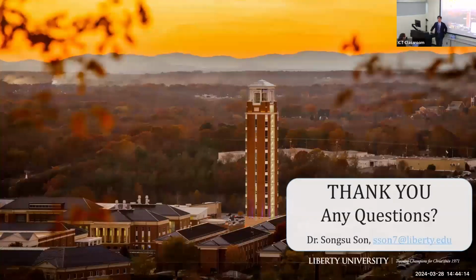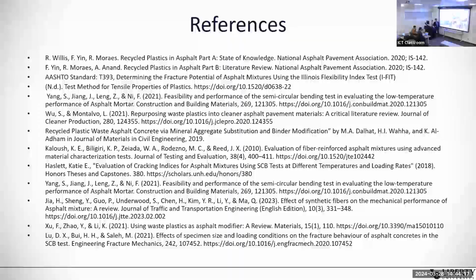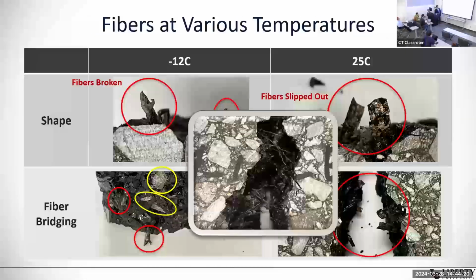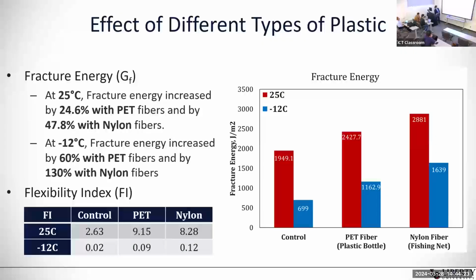Yeah, thanks. Great presentation. Can you go back to the slide where you have the first FI and fracture energy results? Probably this one. Yeah, exactly this one. It was interesting. It seems at 25C, the nylon had a much better fracture energy than PET, but FI actually was lower at 25C, which at intermediate temperature seems to me a very brittle material, because it reaches the peak and then has a very high slope as it decreases. And then I noticed your Cantabro, you also had the worst performance for that one, which is also a room temperature test.